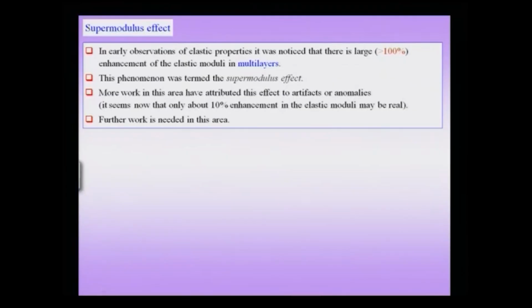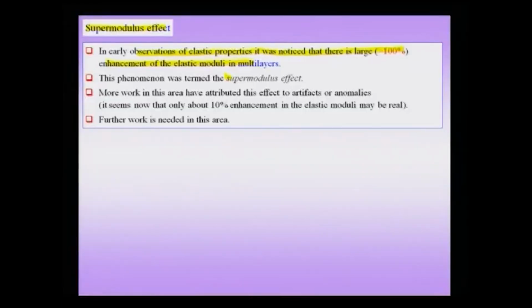there is some effect which is described as the supermodulus effect which was observed, and there was a lot of excitement related to that, and these observations told of elastic properties, as large as more than 100% enhancement in elastic modulus of multi-layers. So, I am talking about thin film multi-layers, and they saw a huge increment in the modulus, and they called this the supermodulus effect. Now, later investigators of course could not confirm the supermodulus effect, and this work showed that this could be because of artifacts and anomalies.